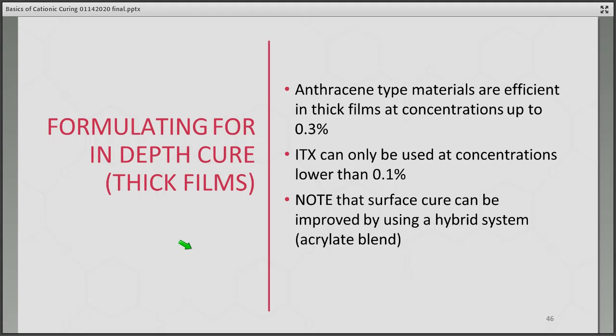We talked a little bit earlier about formulating for in-depth cure for very thick films. Again, anthracene type materials are very efficient in thick films at concentrations up to 0.3%. So you don't need to add a lot for them to be effective. ITX can also be used. Here, ITX tends to be effective at concentrations lower than 0.1%. When you have a thick film that you're trying to cure, you can also help the surface cure by perhaps using a hybrid system, an acrylate blend. We'll be talking more in depth on hybrid systems following this section.